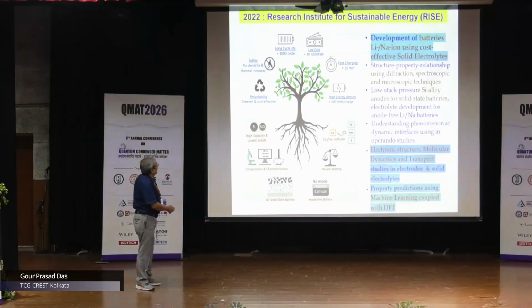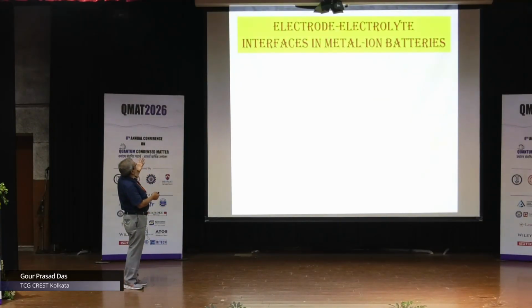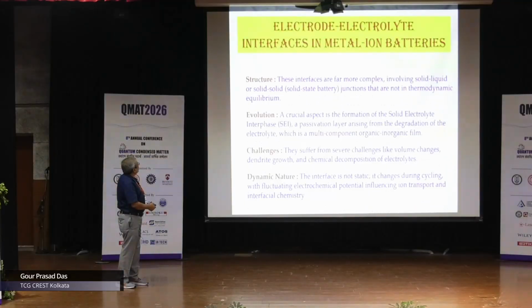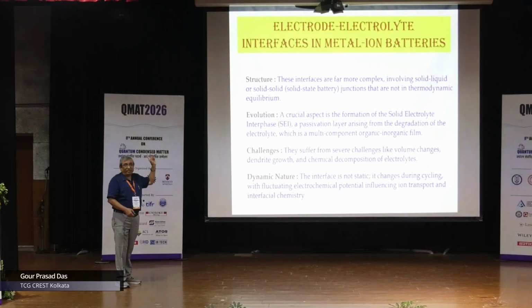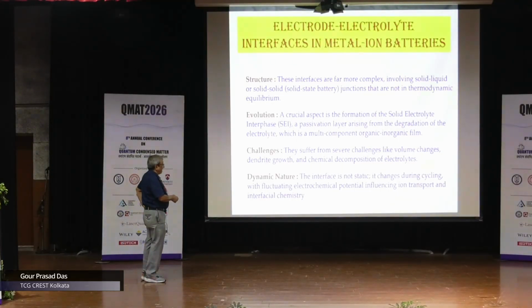But why? Again, we find that the electrolyte interfaces in metal ion batteries play an extremely crucial role. Once again, interface. Now, the structure, these interfaces are far more complex compared to whatever I showed you so far. These interfaces, the electrolyte, are far more complex, involving solid-liquid or solid-solid junctions in solid state batteries that are not in thermodynamic equilibrium. Evolution, a crucial aspect for the formation of solid electrolyte interphase, a passivation layer arising from the degradation of electrolyte. Very difficult thing to handle accurately. The same kind of accuracy that I talked about so far.